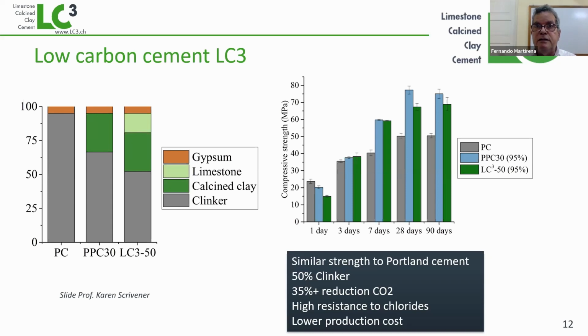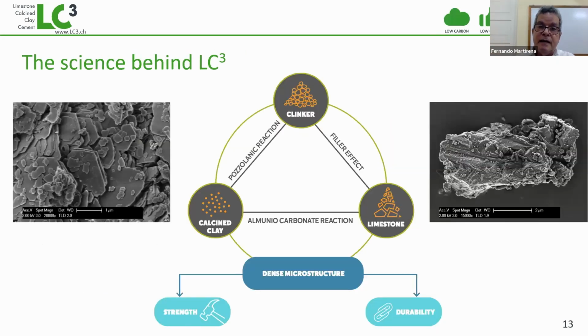But also through the substitution of clinker, you replace 15% more clinker than even Portland pozzolan cement. You're able to make a higher contribution in terms of carbon reduction. But also clinker is the most expensive material in cement production. And since you're reducing this, you also have a contribution to cost. And to our surprise, in the applications we have seen, and it was discussed here before, concrete made with calcined clays has excellent durability. Here's the science behind that.